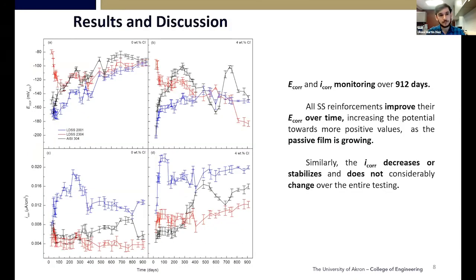First of all, we had the Icorr and Ecorr monitoring of the 2.5 years of exposure. As we can see, we selected both extremes, the 0 and 4% weight of chloride. For the 0, we had the highest, most noble potential for all 3 alloys, stabilizing, reflecting in lower, stable current densities. However, when the chlorides were added, this stabilization happened at lower potential, so more active, with a difference of about 100 to 80 millivolts compared to the non-chloride samples.